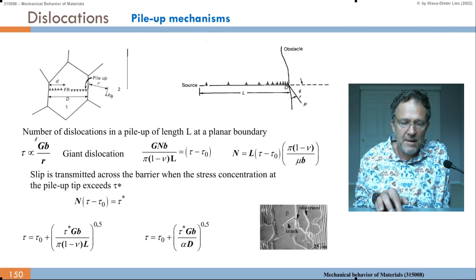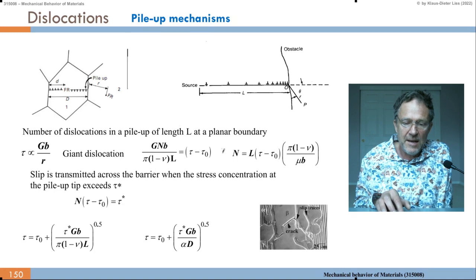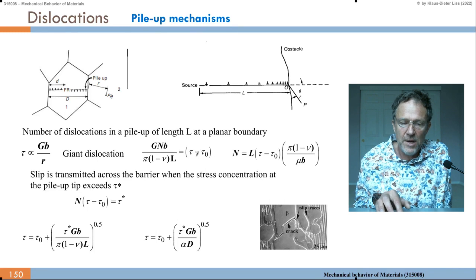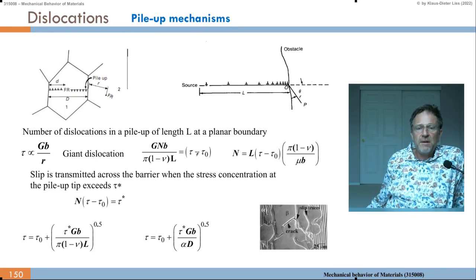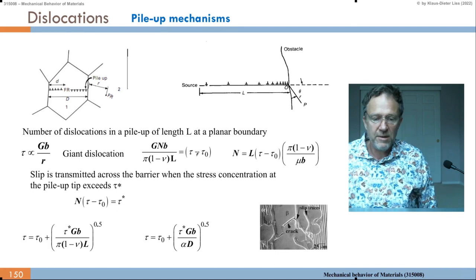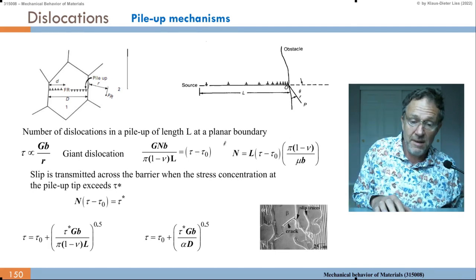But you see this is proportional to Gb over r, and now we have G times n times b over r, and then the geometric factor is pi times (1 minus nu) over L, because now it's not spherical anymore, it's elongated. So if you do the mathematics, it looks like this. And that gives you an extra shear stress, tau minus tau 0. Tau 0 is needed to move the dislocation at all, so that's a threshold shear stress.